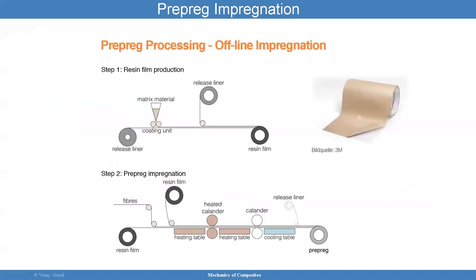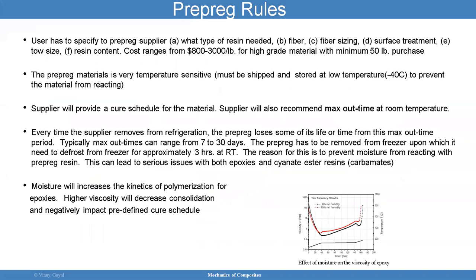Okay, so moving on here, we have prepreg rules. You know, what are some good prepreg rules? The user has to specify to the prepreg supplier. So if you're manufacturing a surfboard, it's up to you to then specify to the prepreg supplier what kind of resin you need, what fiber you need, what fiber sizing you need, what surface treatment you need, and also the resin content. And the cost for this kind of prepreg can range anywhere between $800 to $3,000 per pound. So it's expensive. And sometimes you will have a minimum purchase of 50 pounds. So now you're really looking at high cost for the application.